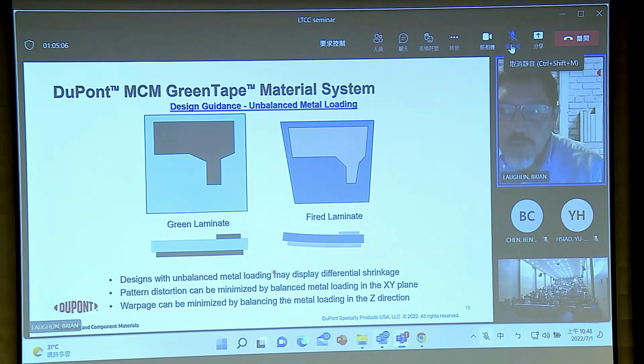One other concept that is a mix of design and process, because it shrinks from the green state to the fired state, and although we make all of our best attempts to make exactly sintering rate matched materials, in the end it's a balance between electrical performance and mechanical stability. And so there is a slight difference between conductor trace shrinkage and the ceramic shrinkage, and I think you'll see that in any LTCC process or set of materials.